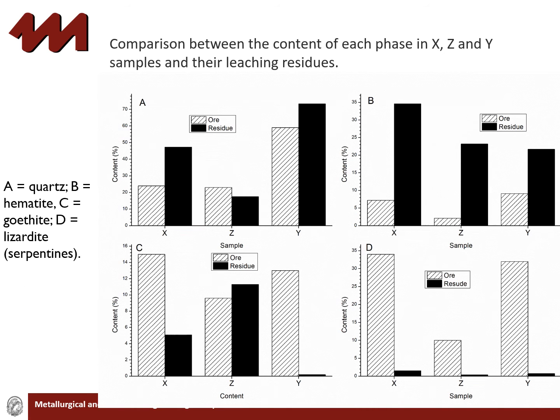The relationship among the four main phase components found in the samples X, Y, and Z and in the processing residues is presented in this figure. It can be noted that quartz and hematite content in the residues increased substantially in relation to their concentration in the original ores. This increase is essentially due to the conversion reactions of ferric sulfate formed during sulfation and pre-roasting, as well as the reaction of minerals containing silicon in their structure to form quartz.